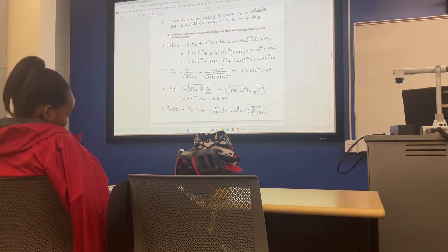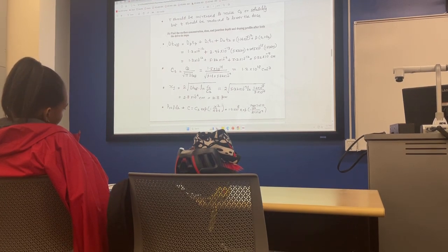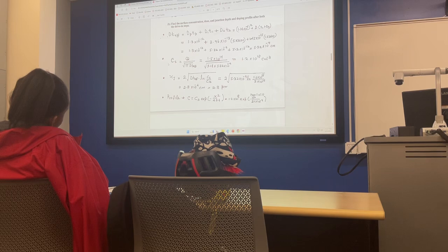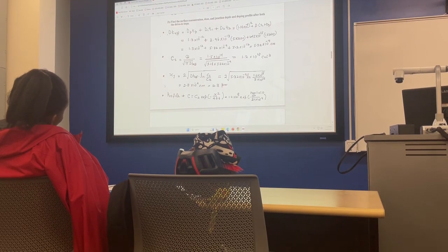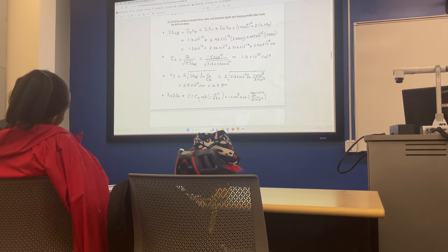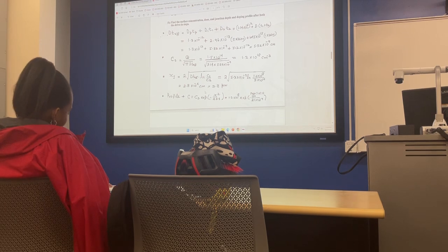Then the Xj equation is simply here. So Dt effective is known. Now you know the Cs from the previous one. The base doping is given to you. That gives you the Xj of 2.8 microns, right? And the third thing is profile. This is all we need: surface concentration, junction depth, and profile. And that is equal to Cs, and Cs is this, times exponential of minus x squared over 4Dt. So this is what we needed to do that. So junction depth is 2.8 microns.